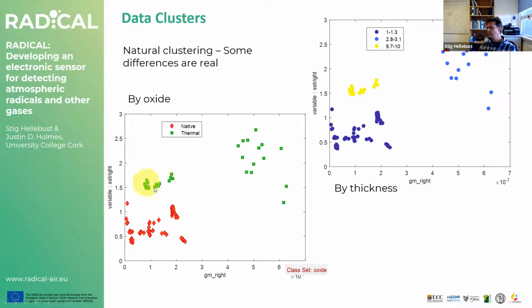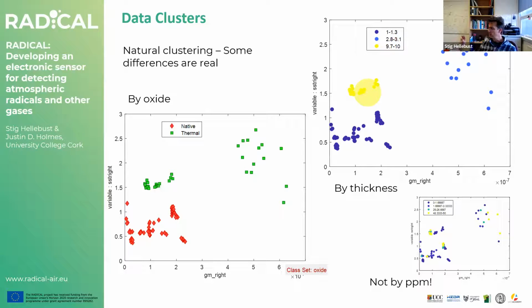And it turns out that the sub-threshold slope is also an important parameter in separating the different oxide thicknesses of the layers. So that's useful information that we can bring with us when we are continuing to develop the surface chemistry of these, but it doesn't get us anywhere in terms of predicting the NO2 concentration. And of course, the purpose of radical is not to detect and predict NO2 concentrations, but we're not there yet that we're testing it on radicals.